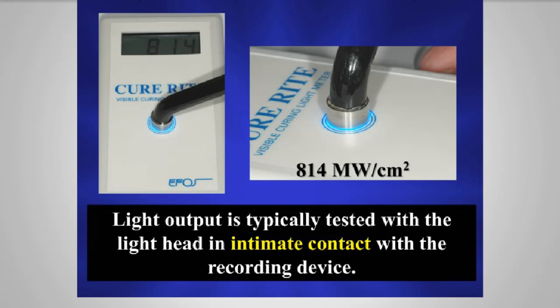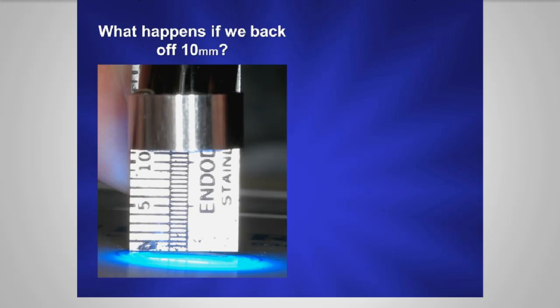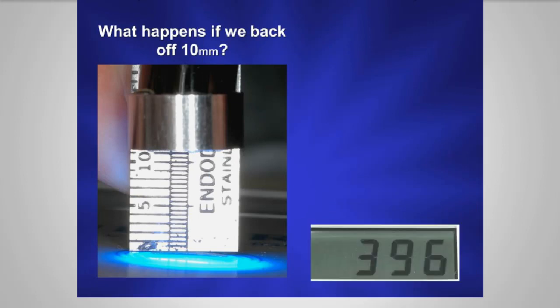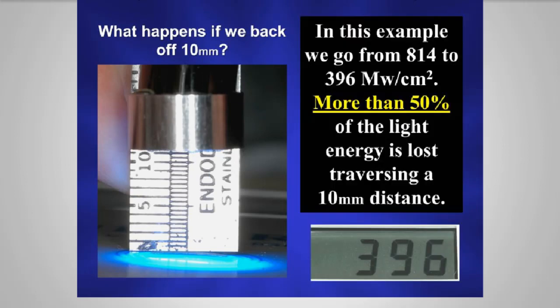I don't care how good your light is. As a matter of fact, the stronger your light, the more percentage loss that you actually get over distance. So I think we need to cure these things longer than most manufacturers are telling us. Distance makes a big difference. So watch your protocol. You don't want your light out here when you're curing your composite materials. You want it as closely and in as intimate contact as possible with the surface of that composite.